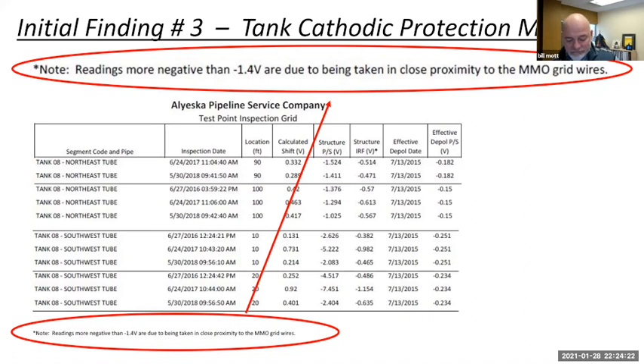In my professional opinion, that reasoning is flawed, because you're interrupting a current. Any electrical field around that grid should collapse, and it shouldn't impact the reading. But regardless of what's causing the error, they're admitting here that there's an error with the data. What they're not picking up is that even if there's an obvious error in this data, there's an inherent error in all of the other data that's collected at the same time, because you've got an interference issue, you've got some other influence. To our knowledge, Alyeska is still collecting the CP data in the same way, despite the conclusions that their consultant, Bob Gamow, provided them 17 years ago.